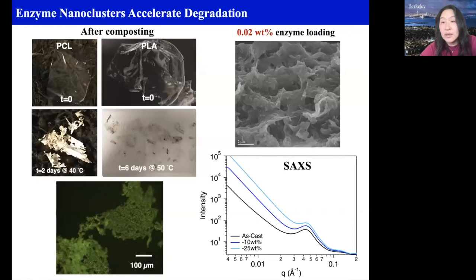And at nanoscopic level, here are SEM pictures of the internal structure of degraded plastic in the middle of degradation. You can see there are a lot of pores. And this again gives us the confidence that the enzyme indeed is nanoscopically dispersed. And this is also consistent with when we look at the small angle X-ray scattering, looking at the crystal structures. So it's not just that by eye you see the plastic disappearing. It's really important to see that they are going to continue to degrade, continue the process.